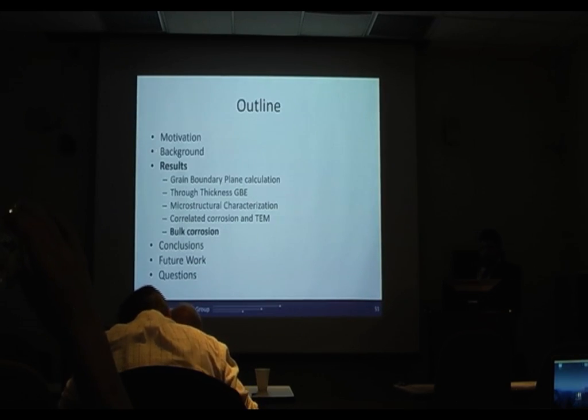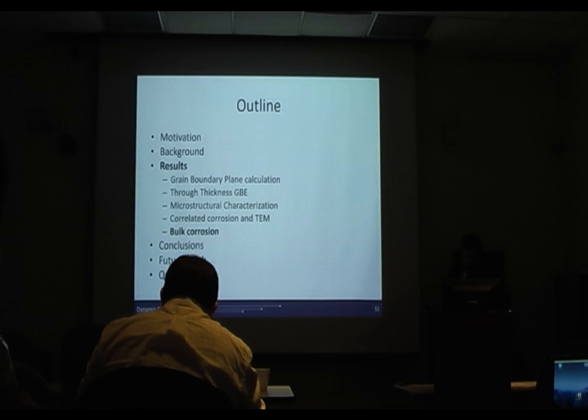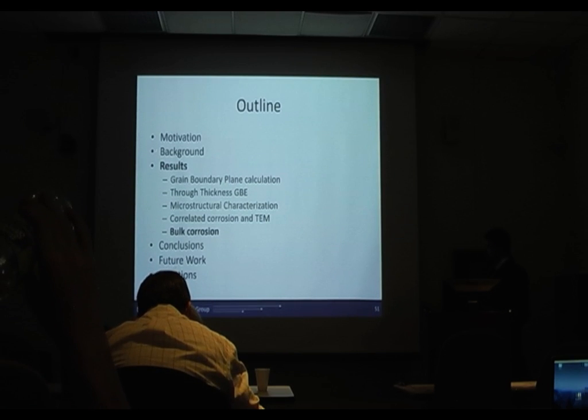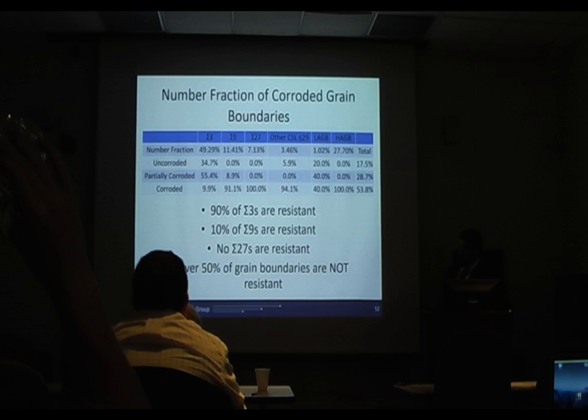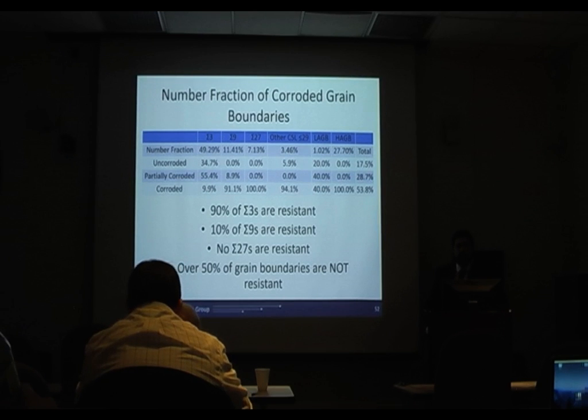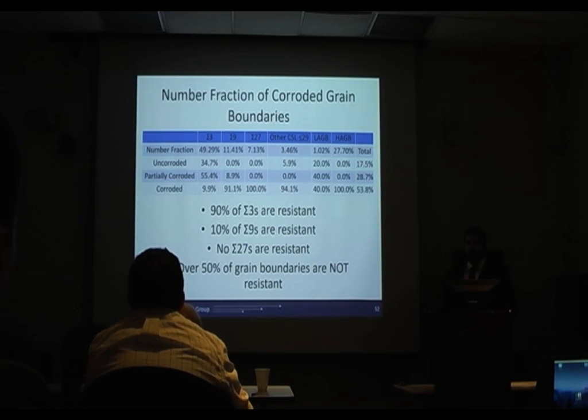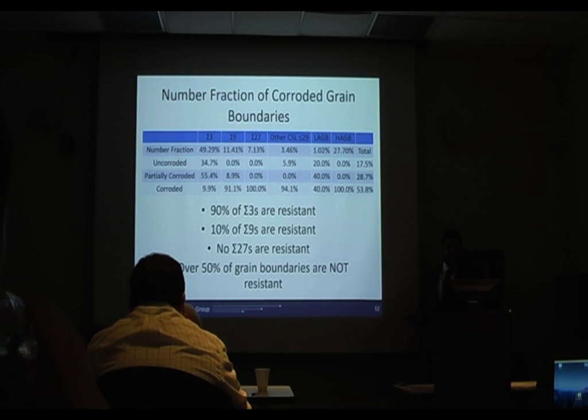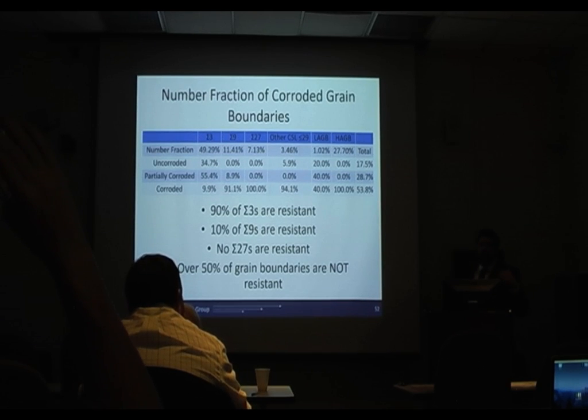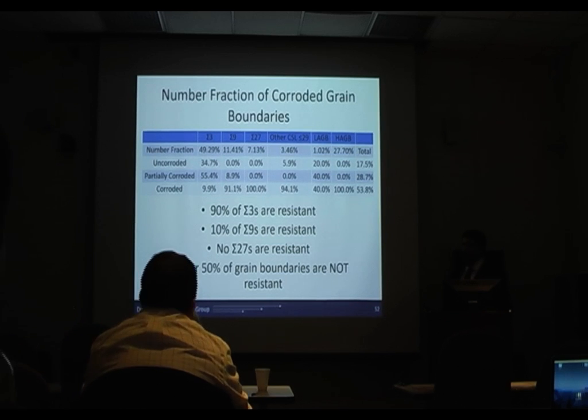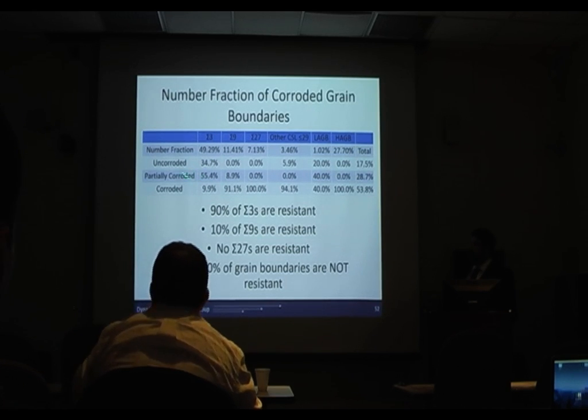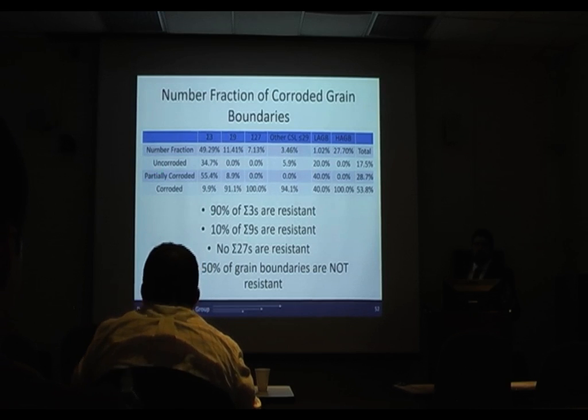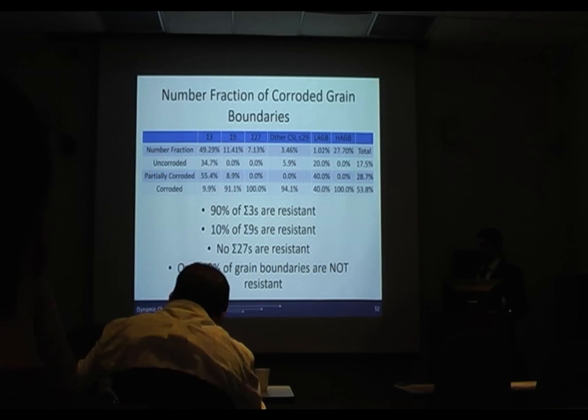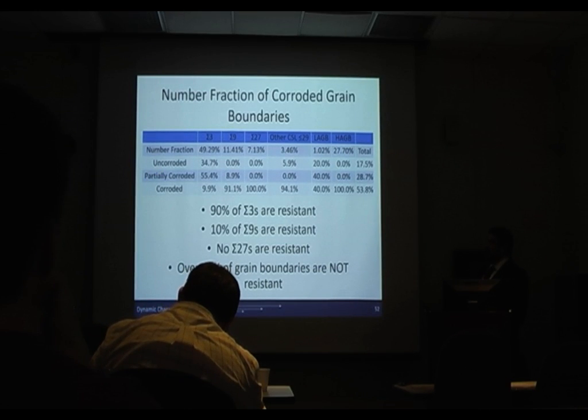So moving on, Chad, slide 51, to the bulk corrosion portion. The first thing we did was those images that I showed with the correlated TEM, SEM and corrosion. I went through and counted the number of grain boundaries that were either completely uncorroded, partially corroded, meaning they had facets that were resistant like we've been looking at in TEM, or completely corroded.